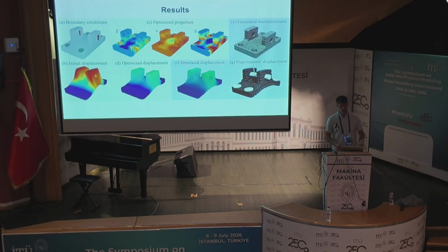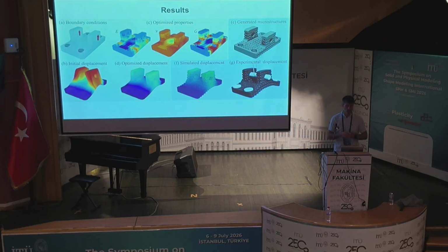And you can now, for example, use this to quickly synthesize optimal stiffness-weight parts. So here you see a pillow bracket for which we ran a coarse optimization for finding the optimal material properties. And then from these, the actual microstructures are generated on the fly and the model is printed.